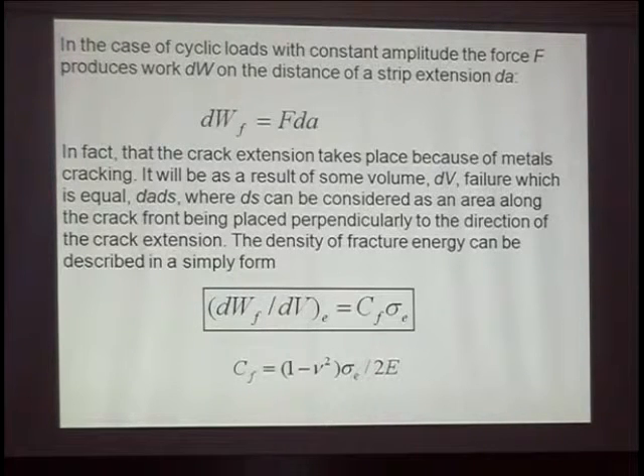It is approximately the same as classically introduced, for instance. But the difference is that there exists sigma E. Sigma E is the equivalent stress, because for material cracking, for string moving, it makes no difference what kind of external loading has been realized, since this model considers only the crack extension. That is why there are different possibilities in complicated ways of external loading, maybe tempering, maybe the influence of residual stresses inside the material. It is complicated. Different combinations between the external and internal state of material can be used to estimate this value.